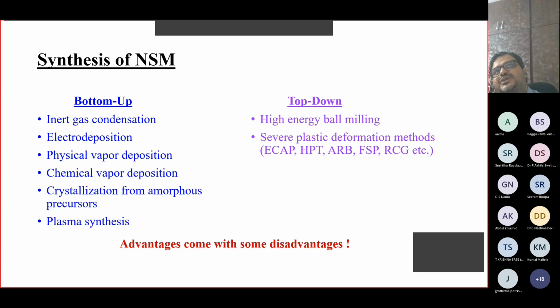Whereas in the top-down approach, you start with the bulk material and disintegrate the microstructure into a nanoscale, for example, grain size or any other particle size and so on. So high energy ball milling is one of the versatile techniques to make a nanometal using the top-down approach. And there exist severe plastic deformation methods that include equal channel angular pressing, high pressure torsion, accumulative roll bonding, friction stir processing, repetitive corrugation and straightening.